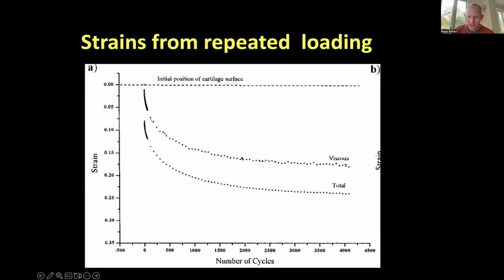And you can see a large fraction of that 22% strain, roughly 17% of that 22%, is viscous strain, meaning strain and deformation happening to the liquid part of the cartilage, pushing and squishing that liquid out of the way. So about 22% total, and about 17% of it coming from strains applied to the liquid phase, meaning only about 5% of that total strain is to the actual damage-prone material,